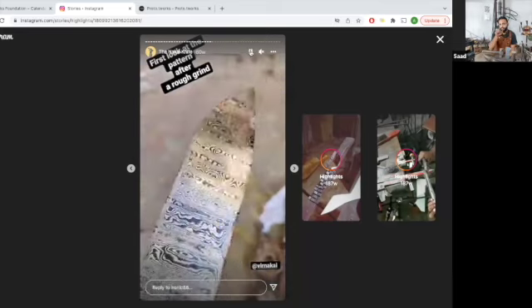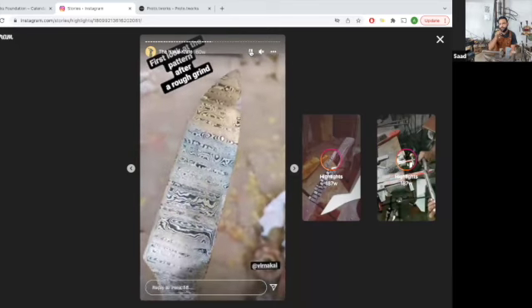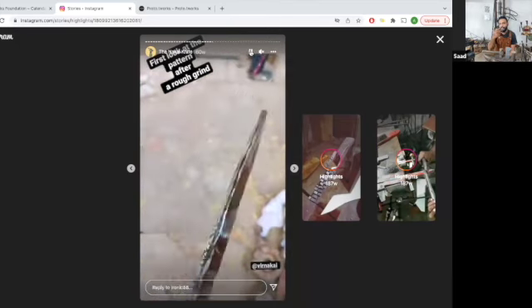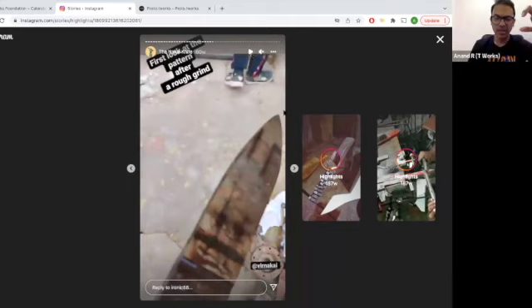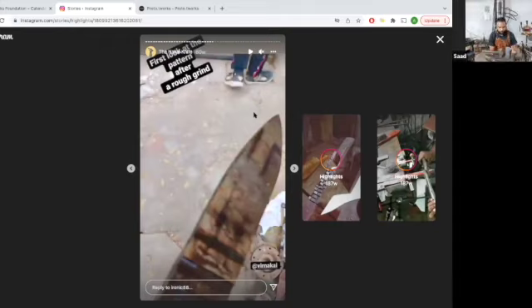All those individual colors, the silver and the black, are actually different layers that have been twisted and hammered into becoming one solid billet. So you get different colors because you're essentially using different alloys where there is a slight difference in the amount of carbon, or there is some impurity in the composition. So you can get either black or silver. If you introduce copper into the mix, it's called kumai, you get copper color also. But that is something that I want to try out later on. Somebody has commissioned a knife with copper in it.